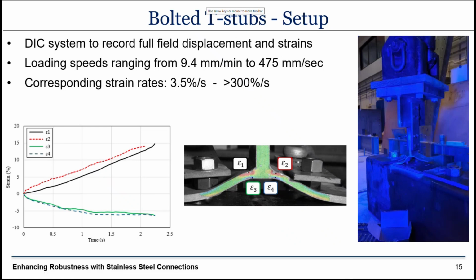To be honest, we wanted to apply similar loading speeds for the lap joints as well. The problem being that we were the first to use the actuator, so we were within the specifications of the actuator, but the technicians had never tested under high strain rates. So we told them what we wanted. They thought they were providing it. At the end of the day, when we went over the results, we saw that we wanted to apply a loading speed of 100, and we ended up with a loading speed of 10 millimeters per second. And unfortunately, it can happen. It's a learning curve.